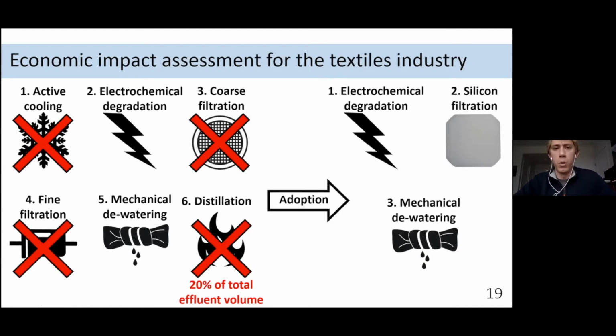So what we think we could do, in concert with talking to a lot of these operators and partners over there in India, is actually erase a lot of these stages, namely active cooling, because our membranes can tolerate much higher temperatures, and then fold in the coarse and fine filtration into a silicon membrane stage. What this would do is ultimately reduce the distillation volume requirement from about 20% of the total volume down to about 2 or 3% of the total volume, if not eliminating it altogether.